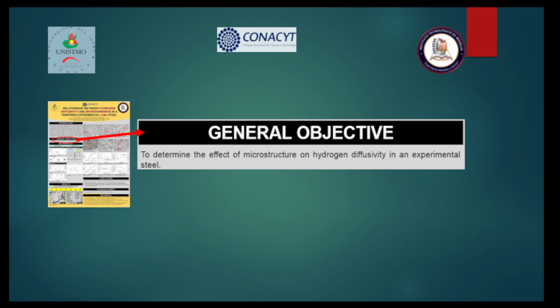The general objective of the work was to determine the effect of the microstructure on the diffusivity of hydrogen in an experimental steel. For that, a commercial AISI 4140 steel was melted to modify its chemical composition by adding a ferroalloy of vanadium and chromium to adjust the chemical composition to 0.3% vanadium. The steel was then conditioned, as explained in this section of the methodology.